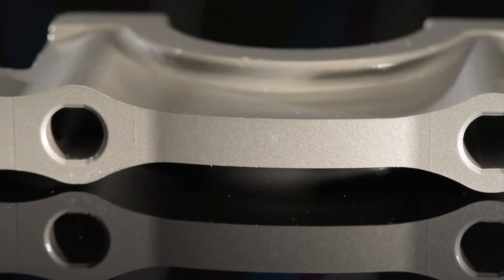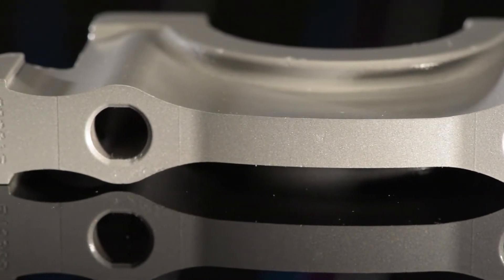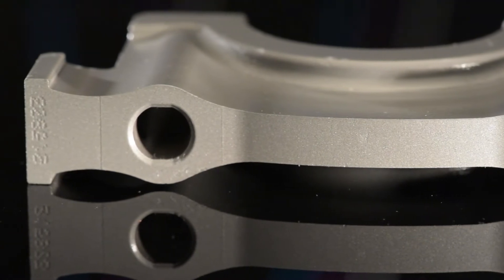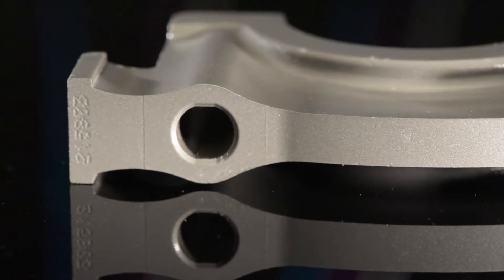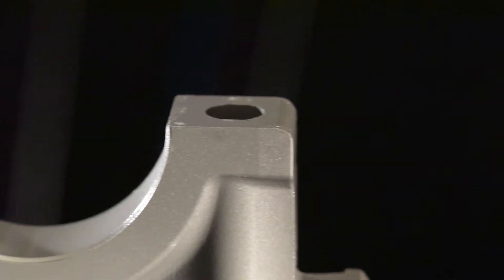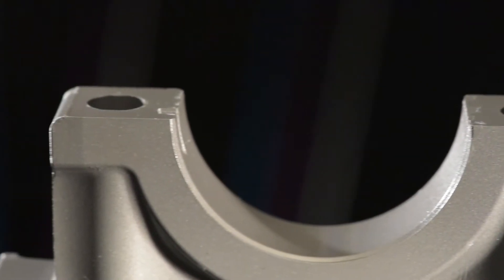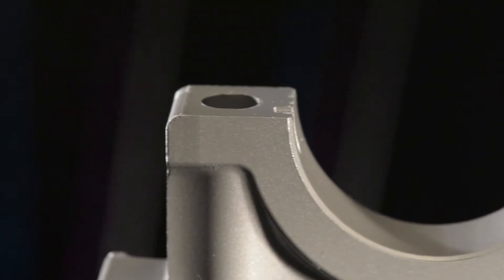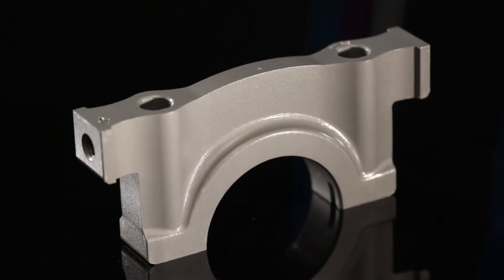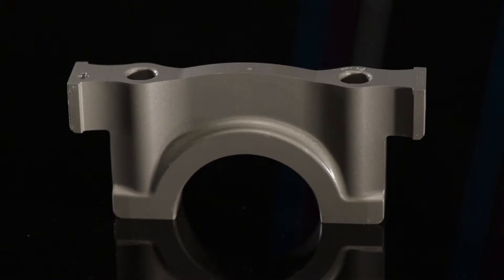The novel design delivers a part that is 23% lighter than previous versions and offers a 10% better fatigue strength. The powder transfer required to form a defect-free part requires the near-perfect choreographing of upper and lower tooling on a CNC compacting press.